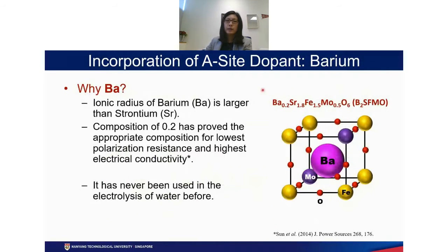And in terms of the selection of this A site dopant, we choose barium because it has a bigger ionic radius than the strontium, but it's not too much bigger. So that could facilitate the smooth doping in this SFMO. And there are some studies before that also show that 0.2 of dopant is appropriate composition for the lowest polarization resistance and also the best electrical conductivity. So we just start with 0.2. And in fact, we tried to survey different compositions, but this 0.2 still gives us the most stable kind of phase. So we stay with this 0.2.